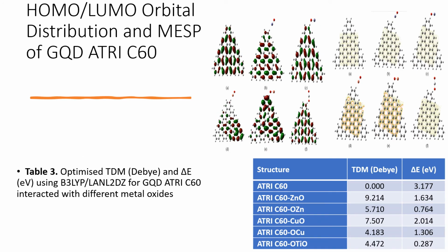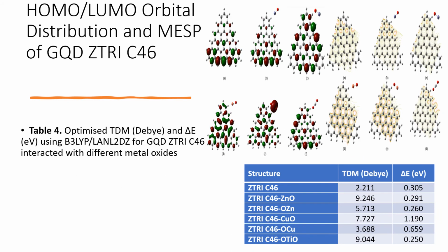Also, in the case of graphene quantum dot with armchair triangle shape, the orbital distribution and the color map of molecular electrostatic potential of the structure were changed, and the reactivity of the quantum dot surface also changed. The total dipole moment increased while the band gap decreased, and the most enhanced metal oxide was titanium dioxide with band gap equal to 0.2 electron volt.